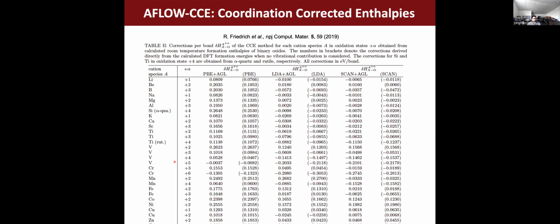This publication, which appeared in 2019, has a nice table of corrections which are based on the species and its particular oxidation state, which correlates to its coordination in the material. We derived the corrections not only based on the enthalpic contributions from raw DFT, but also incorporating thermal contributions, that is, vibrations. Those corrections have been provided here in this table.